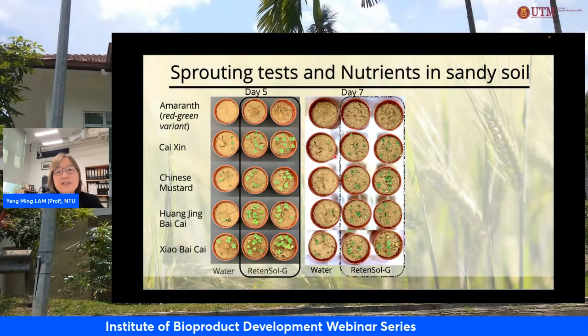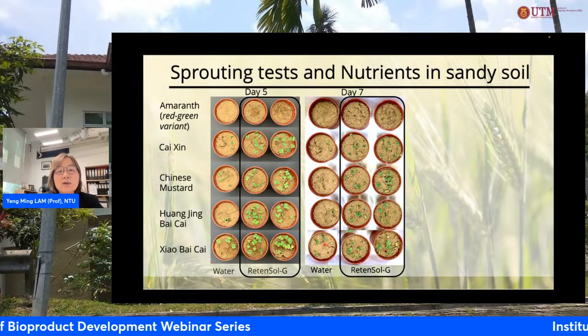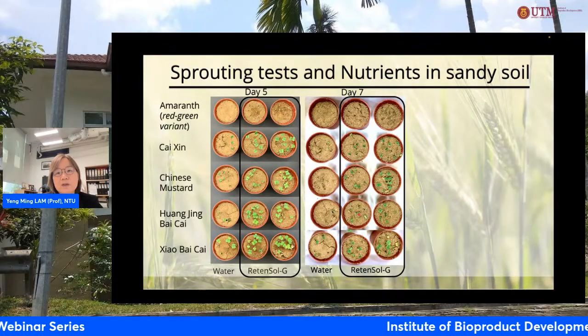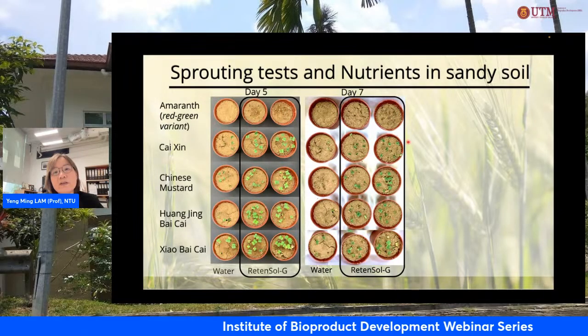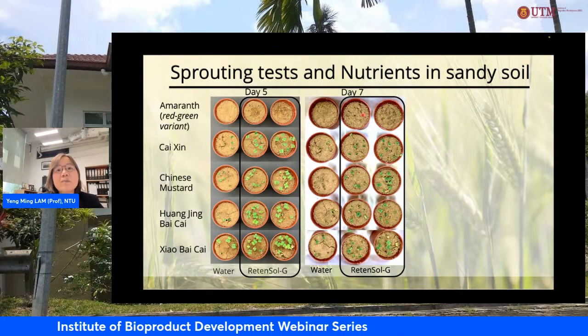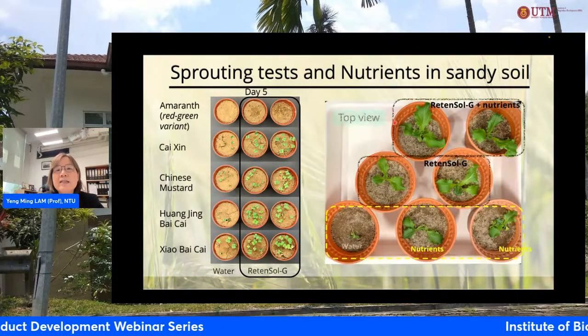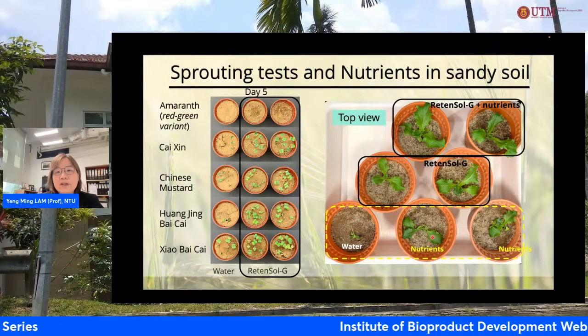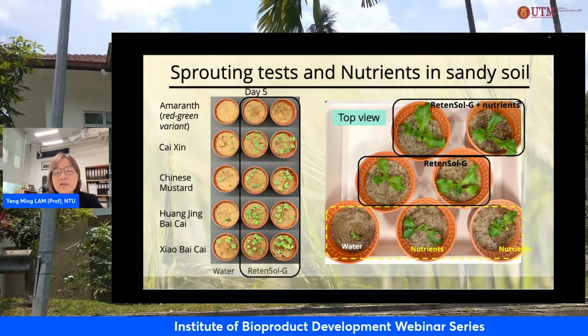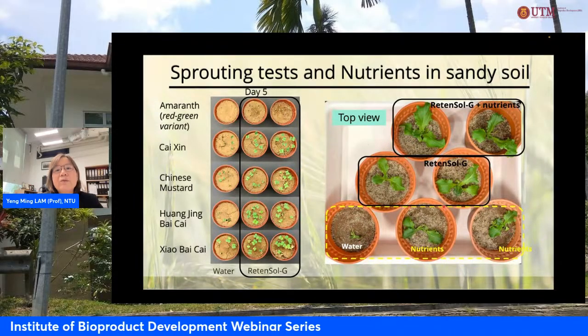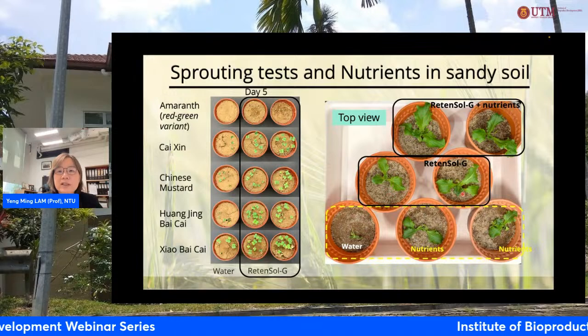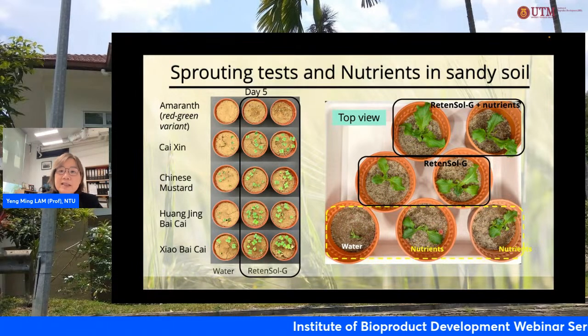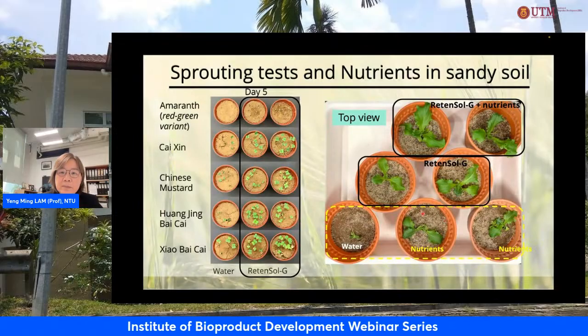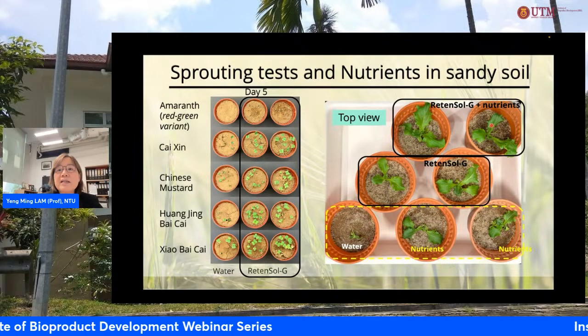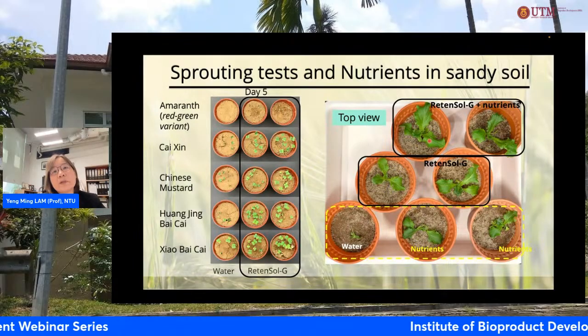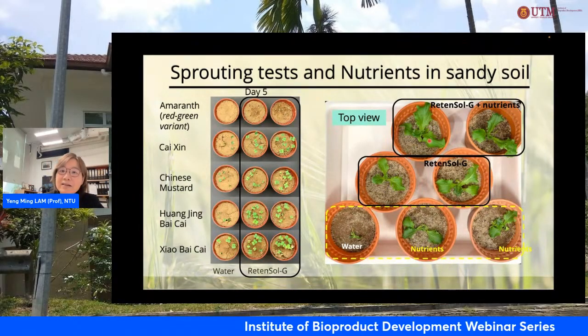If you go to day 7, it's even more pronounced. Most of the seedlings in the water-only conditions all did not survive, but with RetenSol-G, you basically see that a lot of them actually survive. In fact, the first one with amaranth, it also survived, but it's just that the color of these leaves is very close to the soil. And with only nutrients, without any of the microgel, without any of the RetenSol-G, this is how the lettuce grew. And with RetenSol-G, with water only, you see that the plant is already growing very much better than the nutrients given plant pot. And with RetenSol-G and nutrient, the plants is growing even better. So essentially, this microgel helps with plant growth and extend the life of this plant growth.